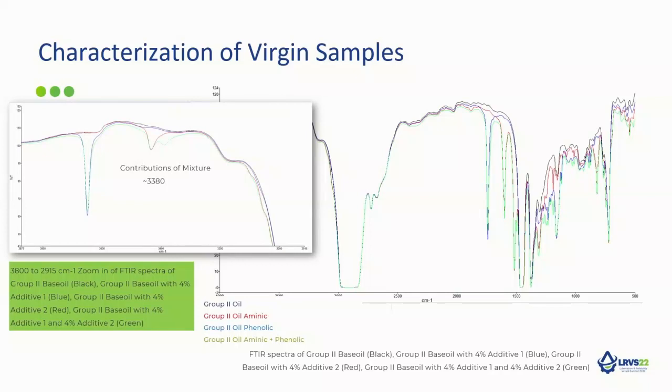We have found that a peak appears at 3380. This is where we begin to scratch our heads, because an apparent reaction is occurring in the same region where we're witnessing NH stretching for secondary aromatic amines. So the question now is, are we creating a new chemical moiety? Are we seeing hydrogen bonding? Or have we activated a resonance structure?